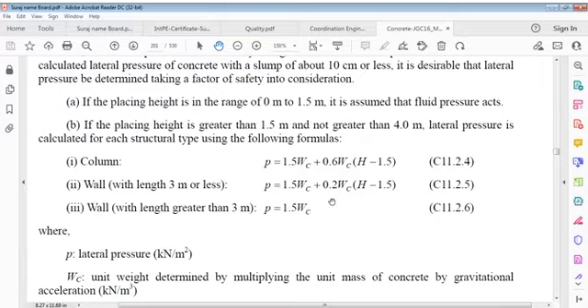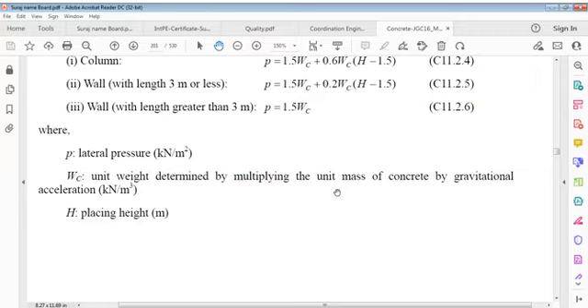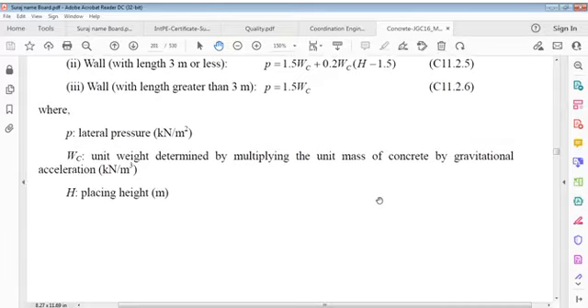If placing height is greater than 1.5 meter and not greater than 4 meter, lateral pressure is calculated for each structural type using the following formula. Column: 1.5 WC plus 0.6 WC into H minus 1.5. Wall of 3 meter or less: 1.5 WC plus 0.2 WC, H minus 1.5. And wall with length greater than 3 meters: 1.5 WC. This is a general trend line. Here the pressure is lateral pressure and WC is the unit weight of concrete, multiplying unit mass of concrete by gravitational acceleration. Placing height is H.